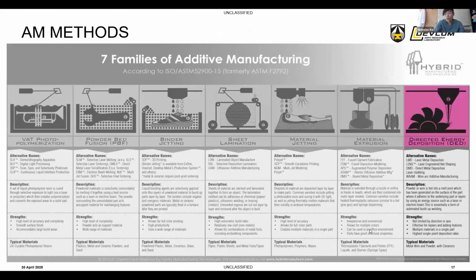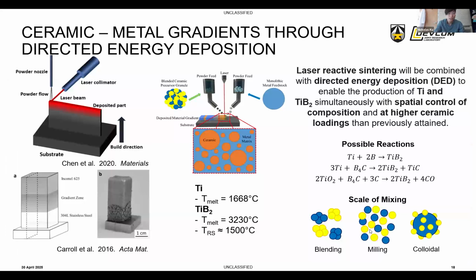Switching gears again, directed energy deposition is an area that we're pretty interested in. This is an AM technique where you're basically spraying powder at a laser, almost like spot welding material. You create a pseudo melt pool at the point where you're spraying your powder, where the laser beam's hitting. You can see a schematic of that on the upper left. It's primarily used with metals, and we're trying to enable it with ceramics.